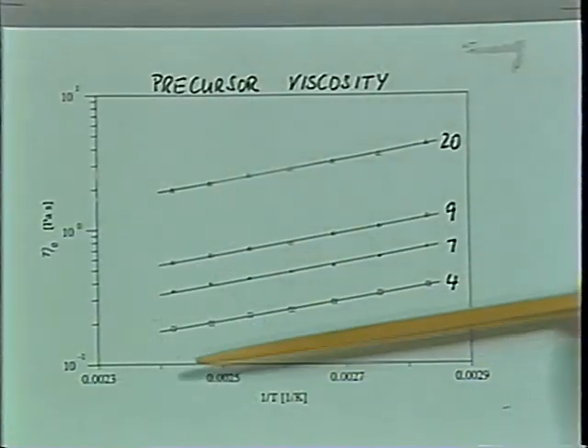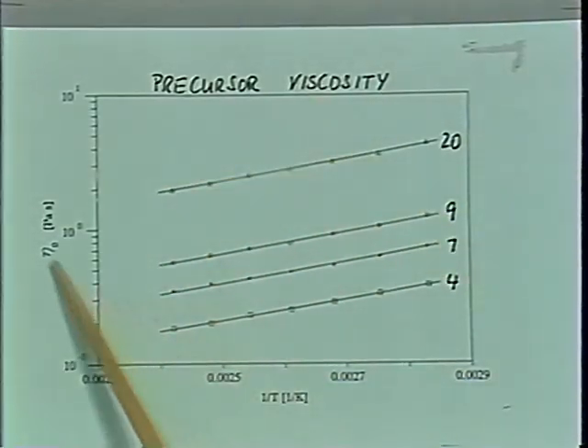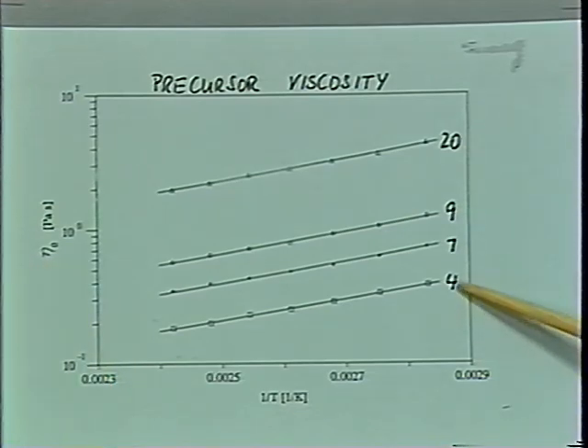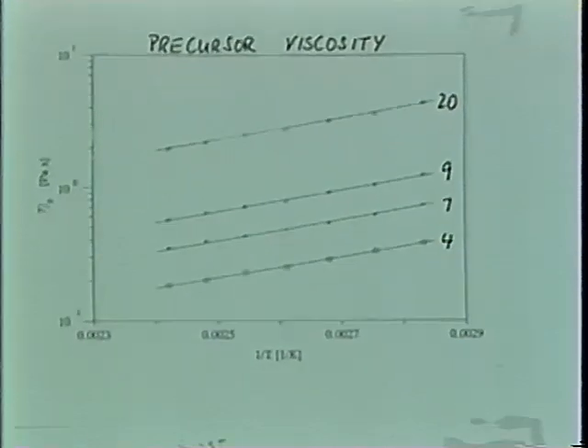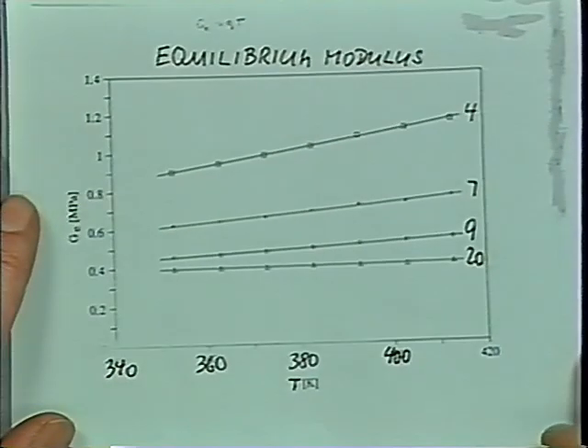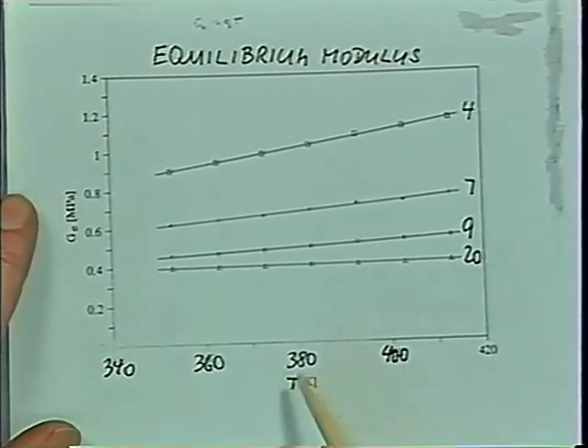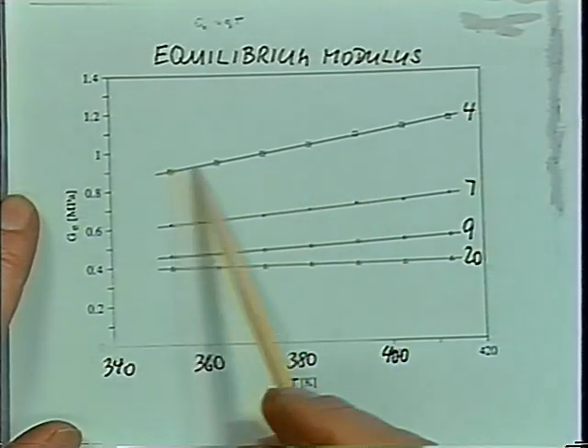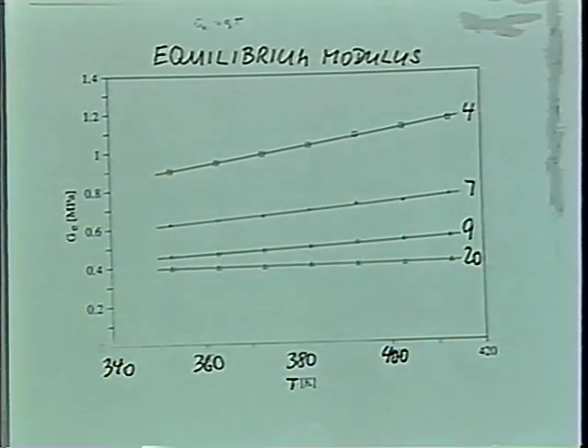He got the shift factor here. This is the precursor viscosity for the 4 samples here as a function of 1 over temperature. So you can see the linear Arrhenius plots. We are far away from the glass transition. And the equilibrium modulus is proportional to the temperature. And that's already a surprising result.